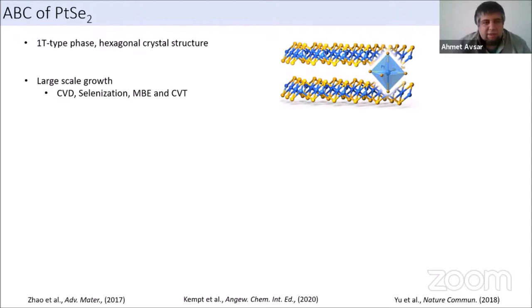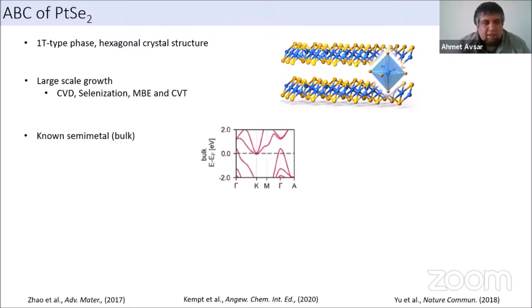And this material can be grown through different methods. For instance, you can use chemical vapor deposition, selenization, molecular beam epitaxy, and also chemical vapor transport to grow this material at large scale. So this also means that if you want to do any application based on this material, it's doable. The technology is already there. And this material has indeed different types of electronic structure. So indeed, for a long time, it was known that the bulk of this material is a metal. It's a semi-metal, okay?